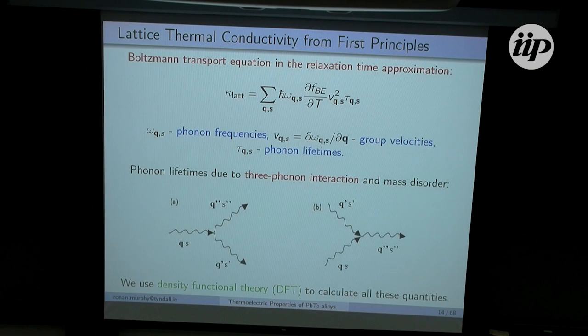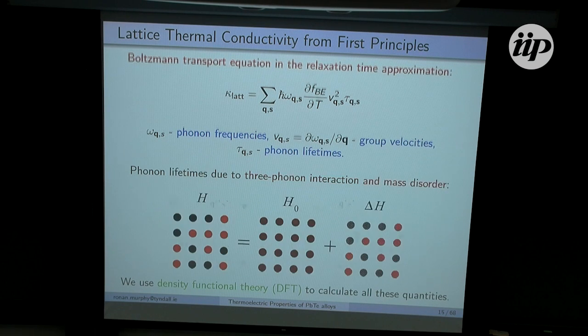So to start off with, we go to the Boltzmann transport equation in the relaxation time approximation, where omega are the phonon frequencies, v are the group velocities, and tau are the phonon lifetimes. Now, in order to calculate these phonon lifetimes, we model them first of all due to 3 phonon interactions, neglecting higher order interactions. This is where, say, 1 phonon scatters to give 2 new phonons, or 2 phonons combine to give 1 new phonon. In the second case, we calculate phonon lifetimes due to mass disorder.